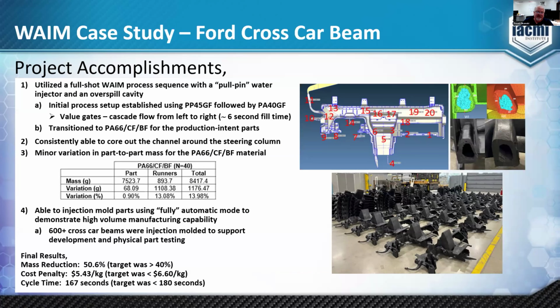What were we able to accomplish? In this particular program, the water assist used the full shot process sequence with a pull pin water injector and an overspill cavity that you can see here that pushed the core of the hot melt material into a puck. The initial process setup was established using a glass-filled polypropylene, which we then transitioned into a 40% glass-filled nylon part. And the valve gates, the 12 valve gates, were cascaded from left to right. So cascaded flow is employed to push the melt front across the part, again, from left to right.